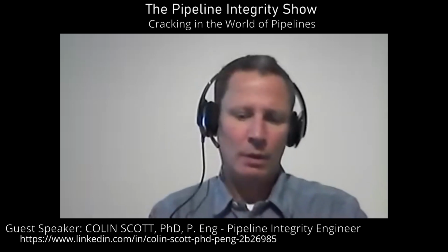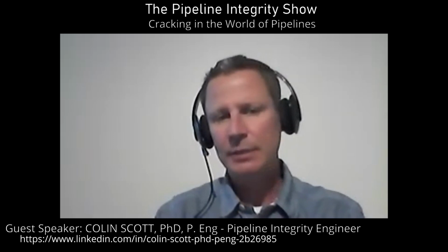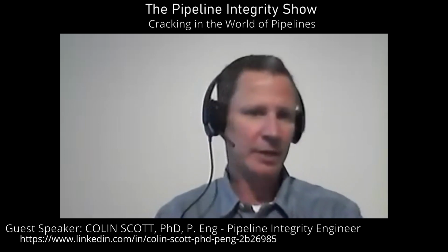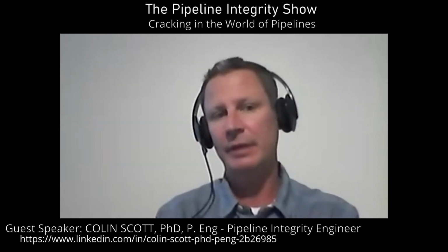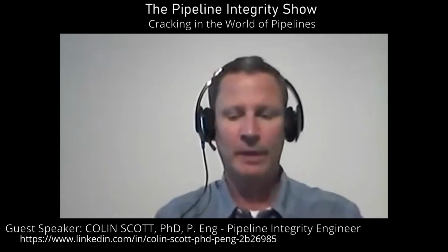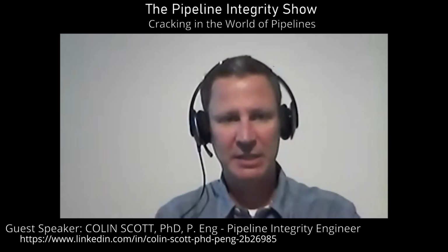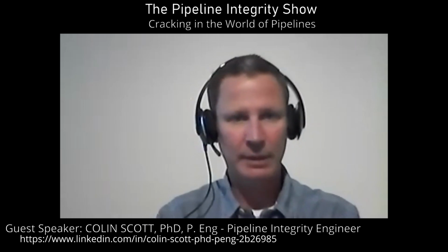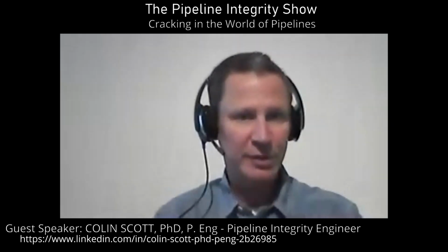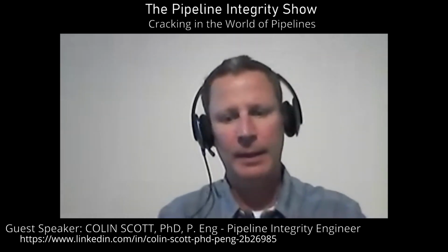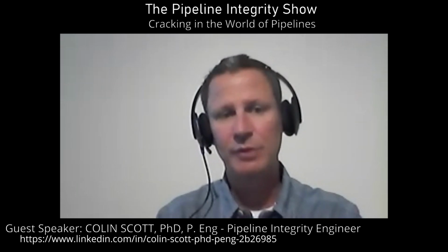Now, with trying to deal with fatigue, the best way to deal with any one of our integrity problems, as you know, is prevention is better than a cure, right? If you can prevent things up front, you should do that. When you look at the 50s and 60s vintage pipelines, they didn't really have great QA. They didn't have great knowledge in how to prevent the defects. And that's something that we've learned a lot from. A modern pipe mill will typically have much better QA processes than they did 60, 70 years ago, and you're just not going to get the same sorts of defects along the long seam weld.